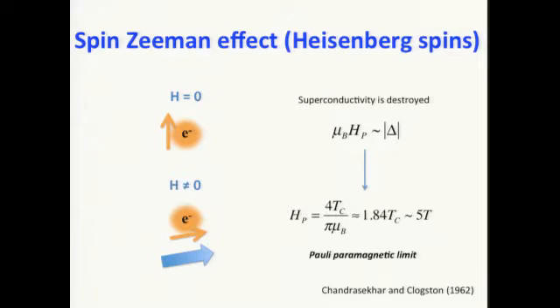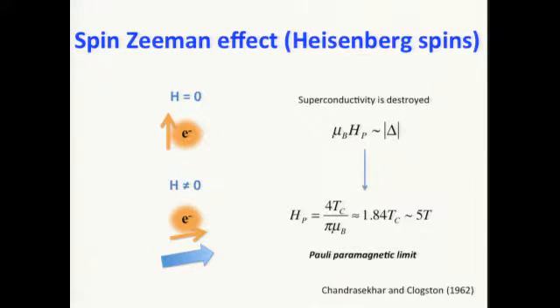So if the material has Heisenberg spins, like in a normal BCS superconductor, under an external magnetic field, the electrons develop a Zeeman energy, which is mu_B, the Bohr magneton, times the applied magnetic field. And when this Zeeman energy becomes comparable to the superconducting gap or the other parameters of the system, then superconductivity is destroyed. This is the spin paramagnetic limit I've talked about. So you can do a little bit of math here. It turns out that this gives rise to the famous Pauli paramagnetic limit, which is written in this simple form. The constant here is 1.84 times Tc in Kelvin, which gives you H_P, the Pauli limit, in Tesla. So for a 3 Kelvin superconductor in the monolayer case, the Pauli limit is about 5.5 Tesla.